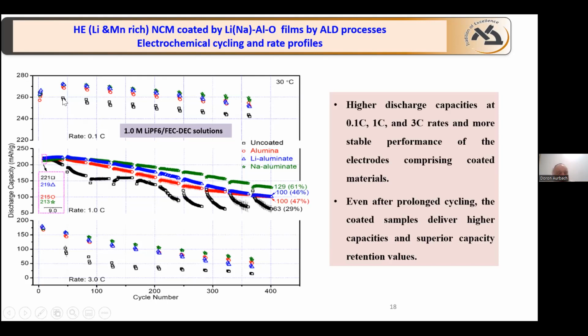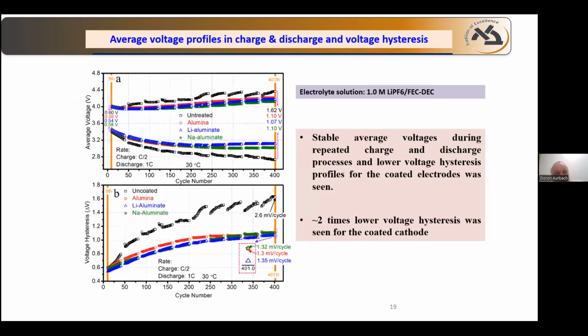And when we increase the rates, we do experiments even at 3C rates, which means discharge and charge during 20 minutes, then we see very nice differences between the untreated material and the treated material. So here, judicious coating does a good job, and whenever we have such stabilization, we stabilize the voltage. So here you can see the effect of useful coating on the voltage. We stabilize the voltage. We stabilize the hysteresis between discharge and charge.